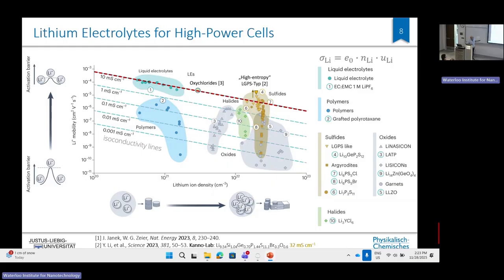You see, they have much lower lithium ion concentration and the mobility already is climbing up. And with the polymer sector, I would say there's not so much improvement over the last years. You can, of course, increase the conductivity if you gellify them, if you add liquid electrolyte into the polymer. But that's not, I would say, a true polymer electrolyte.